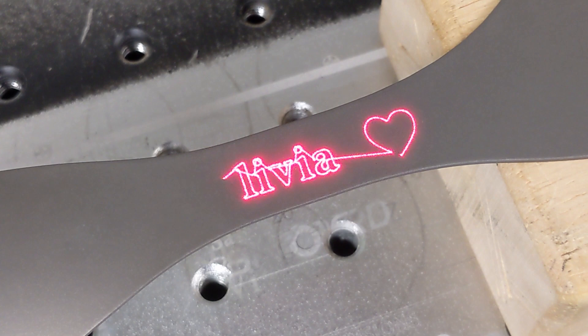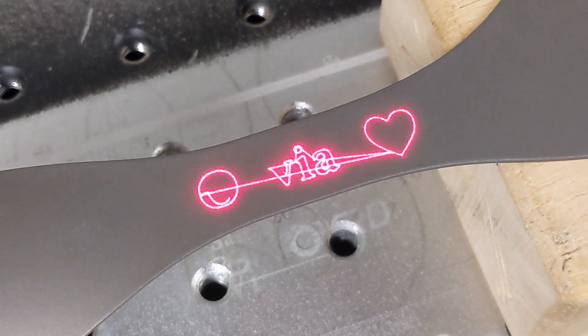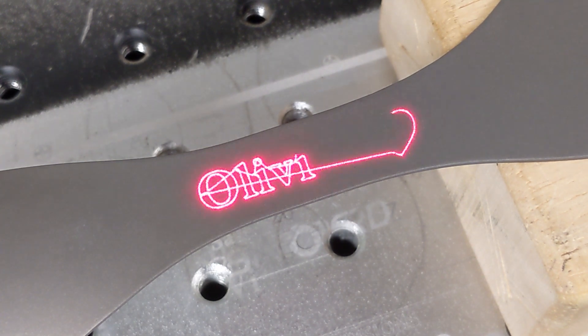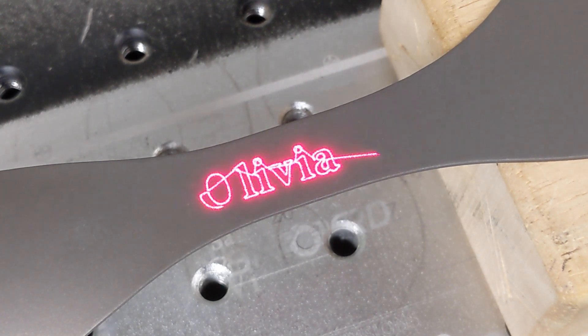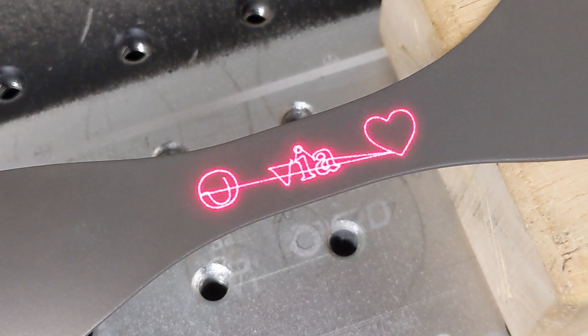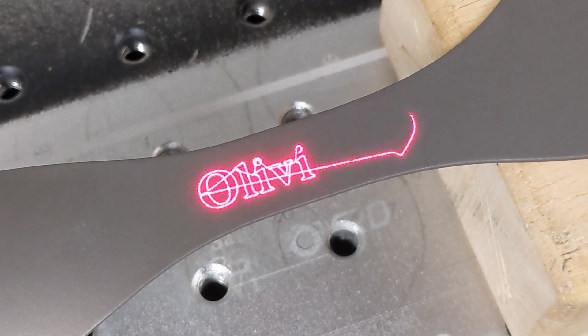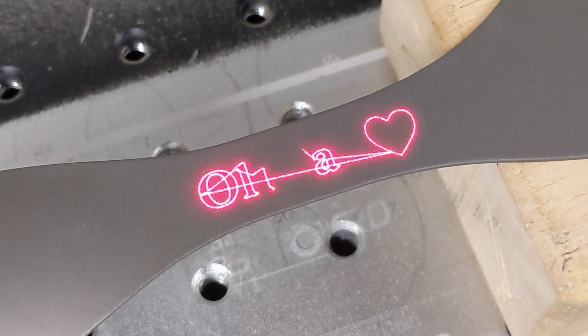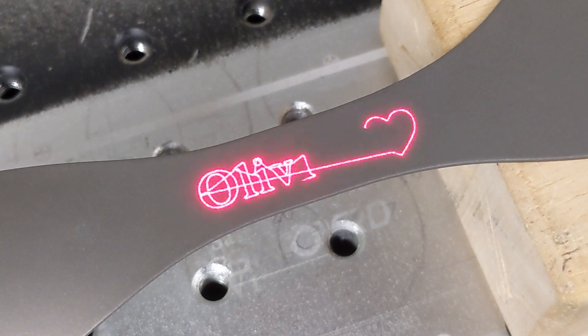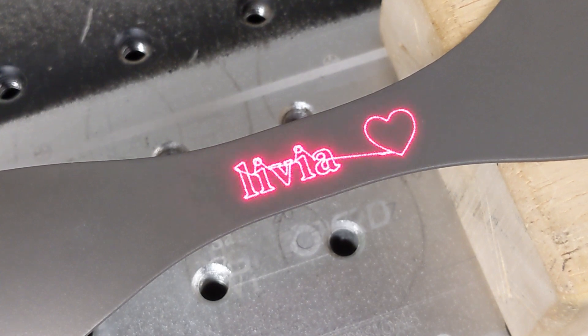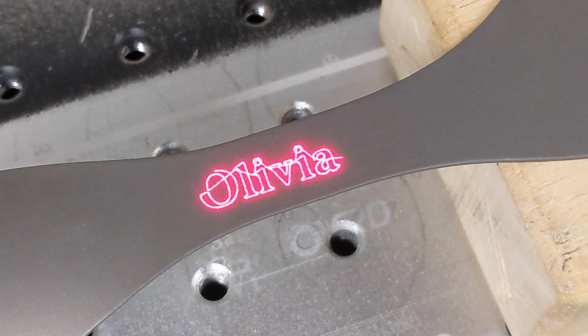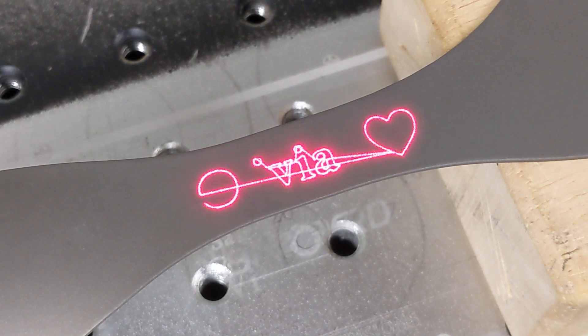You'll notice that we were just starting with three passes. I don't like going too deep on titanium, otherwise we start to see the striations of the hatch pattern in the metal. Titanium reflects that really well, so we're going to keep it light and simple today. Just three passes, and then we'll follow it up with an anneal, and we should be left with something that looks really great. So let's go ahead and get this running.